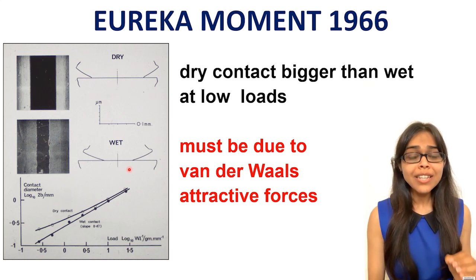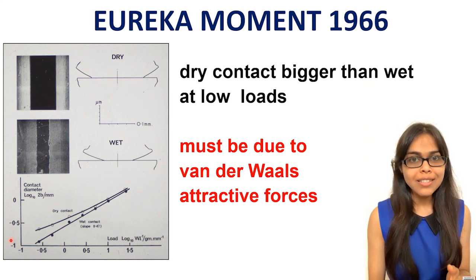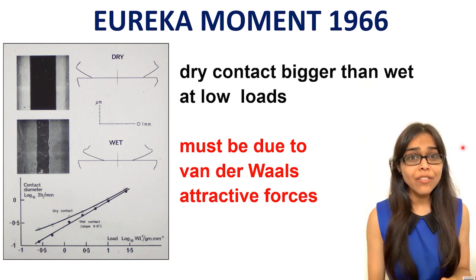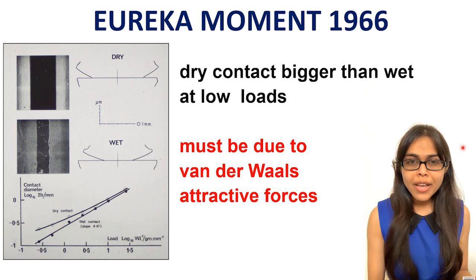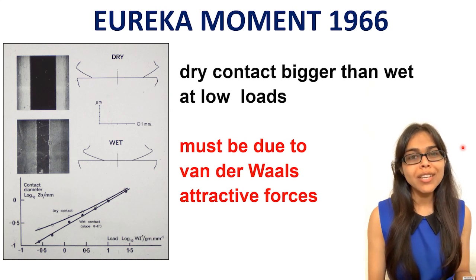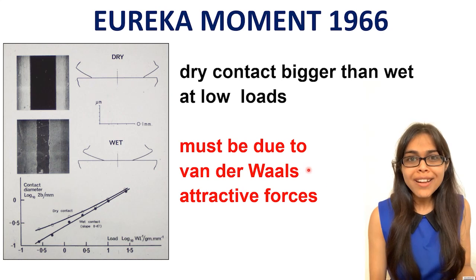The result at the different contact forces, that is, the contact size on the vertical axis, windscreen wiper force on the horizontal, showed that the wet rubber fitted the elastic deformation theory, whereas the dry contact gave much bigger contact area. This big discrepancy seemed to Alan to be the effect of van der Waals force attracting the rubber to the dry glass.